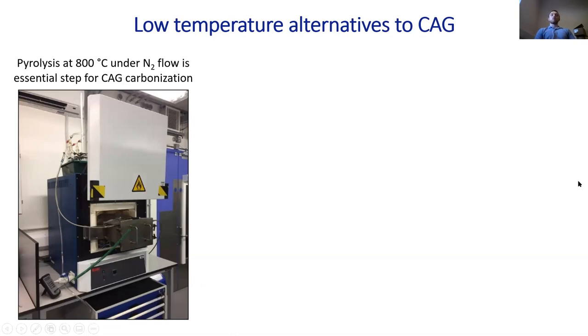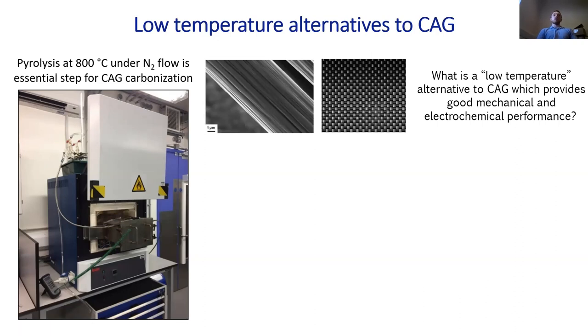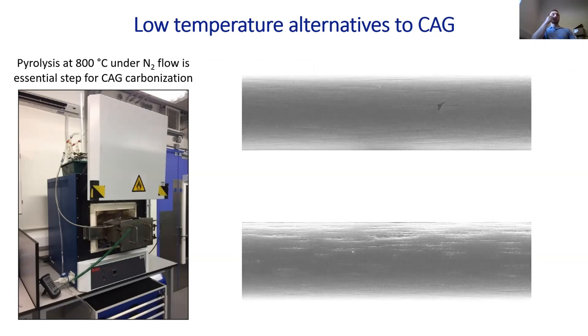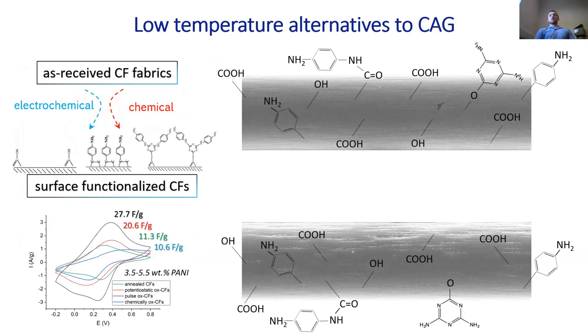So my current project focuses on trying to implement a low temperature alternative to carbon aerogel, which can result in supercapacitors with sufficiently high mechanical and chemical performance. So the way to achieve this, which I consider, is again a multi-step route, which starts with the functionalization of the carbon fiber surface. And this type of functional groups can have quite different nature and can be produced by different methods, which depend mostly on the type of material which we want to deposit on later.